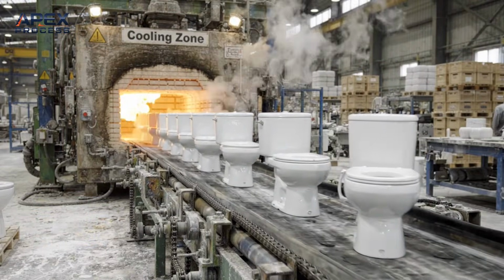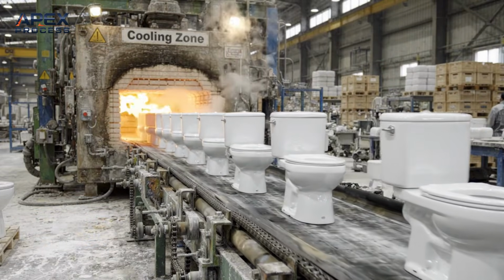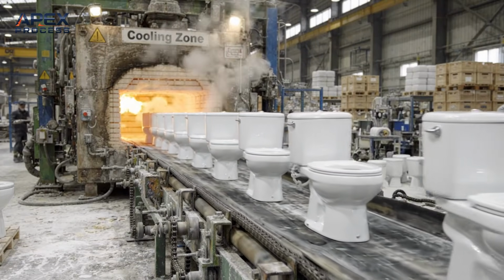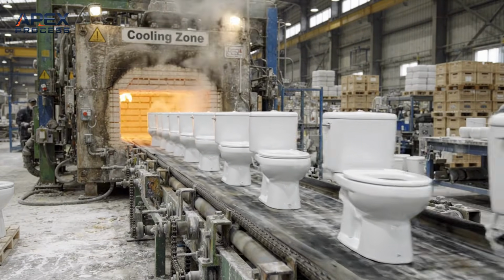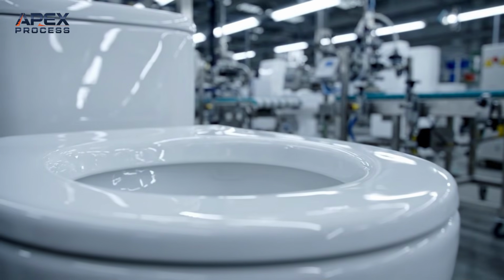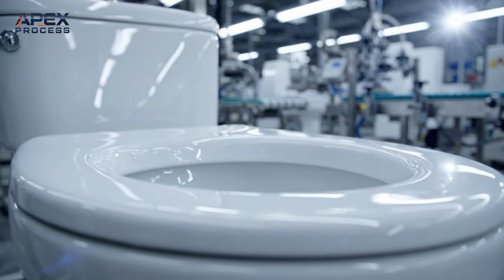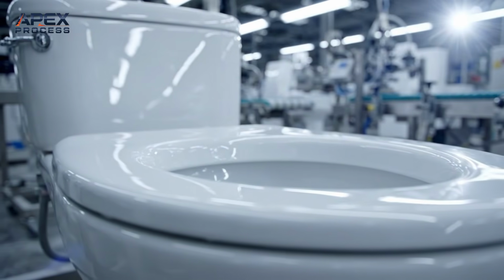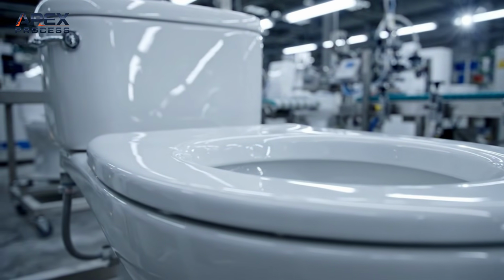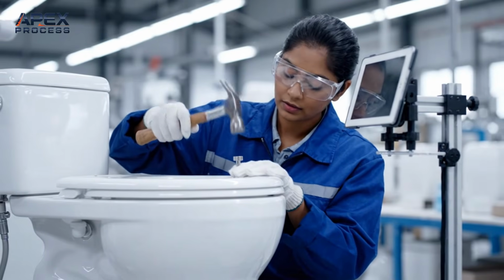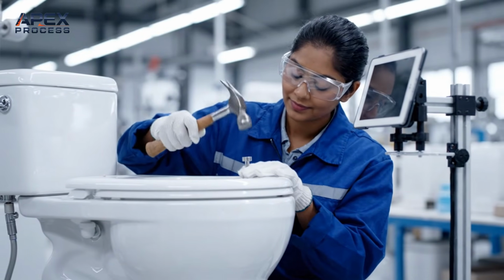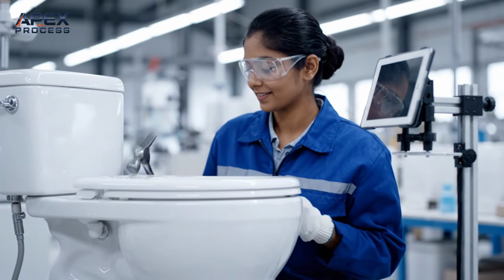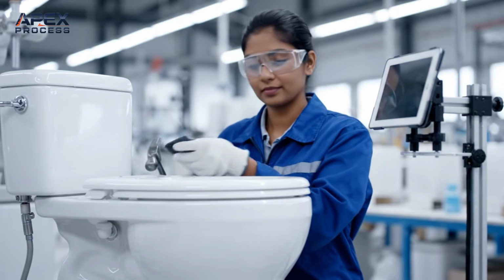The cooling phase. Slow temperature reduction prevents thermal shock and surface cracking. From dull clay to brilliant porcelain, the transformation is complete. The ring test. A clear, high-pitched tone indicates a solid structure with no internal cracks.